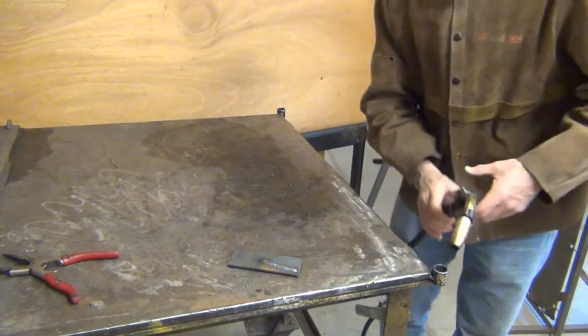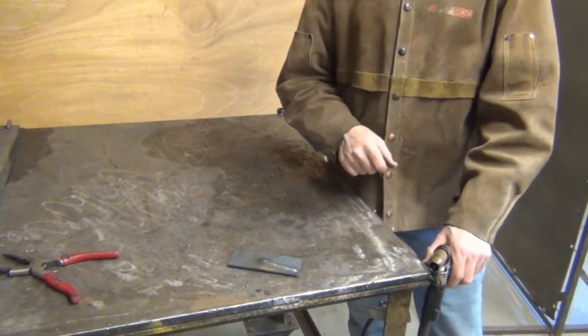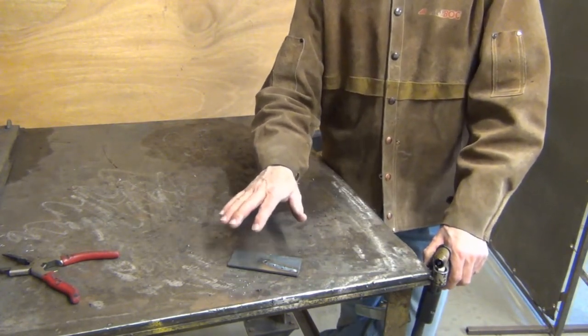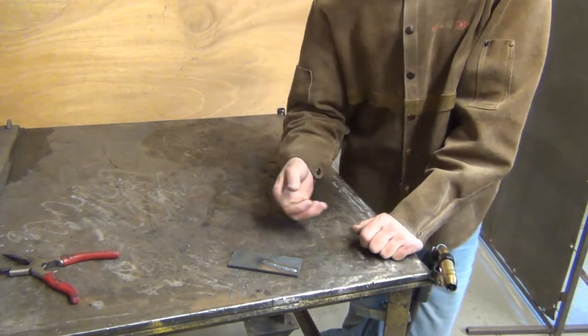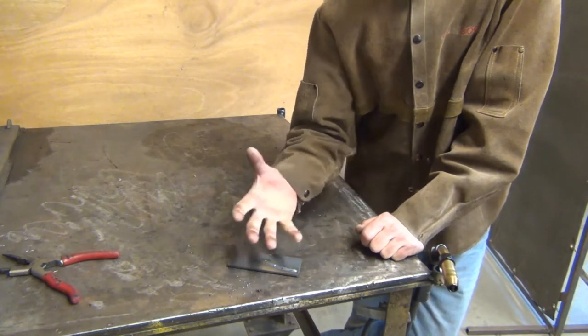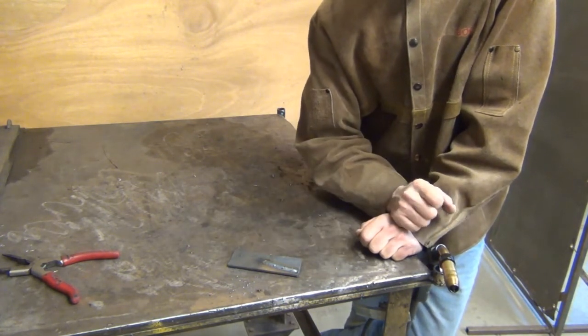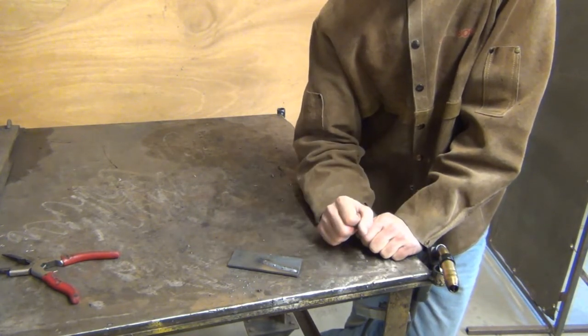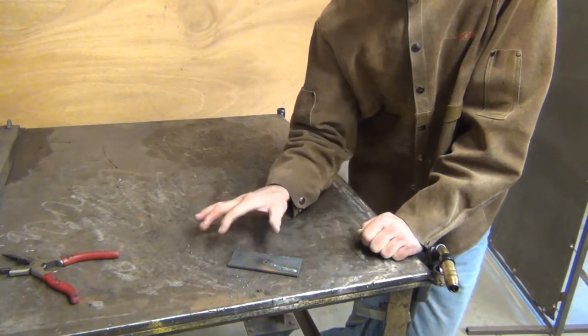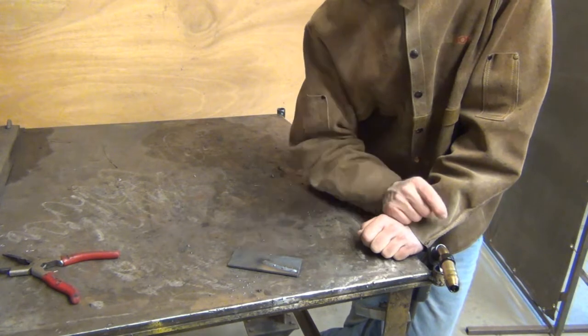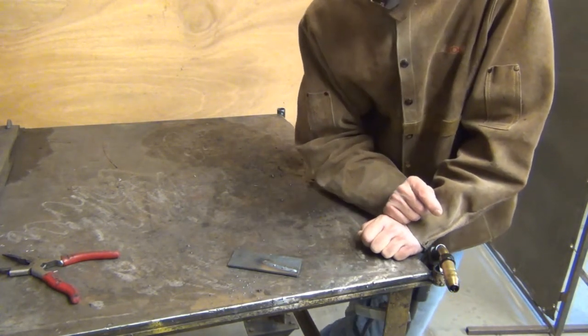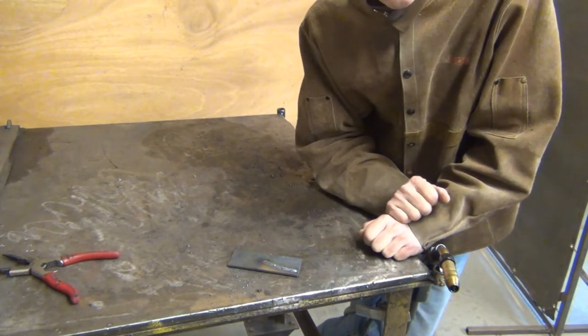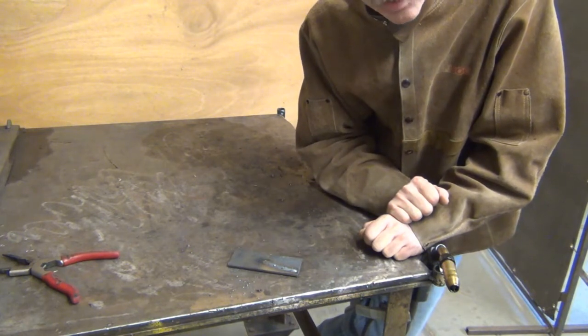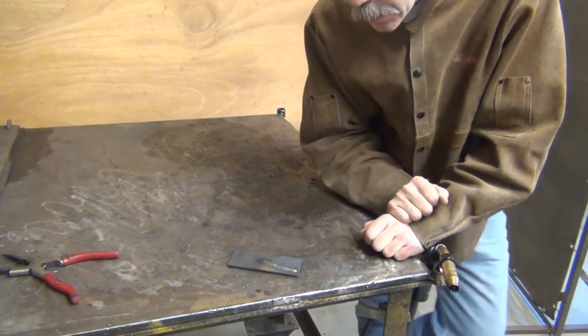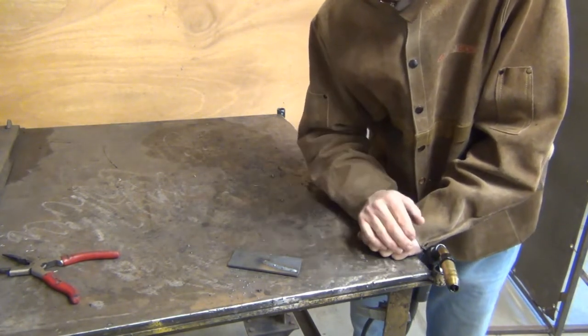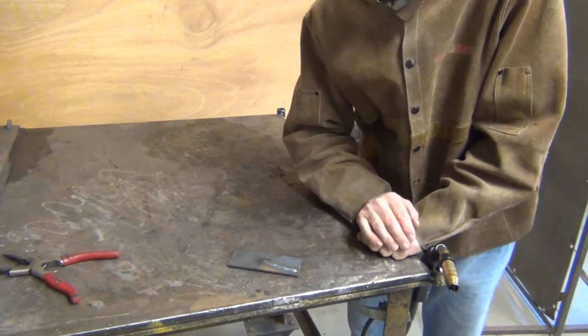When you weld material, it needs to be clean. If the material has got paint, oil, coolant, you've got to wipe it off. It will vaporize, but the problem is that shielding gas. If that is vaporizing off, it's creating quite a turbulence. That shielding gas is no longer able to cover that molten puddle and protect it while it solidifies. You end up with porosity, and that's nothing more than the perforations on the toilet paper. That's where it breaks. Catastrophic weld failure. Okay? So if it's had any of those substances, just give it a wipe with a clean cloth.